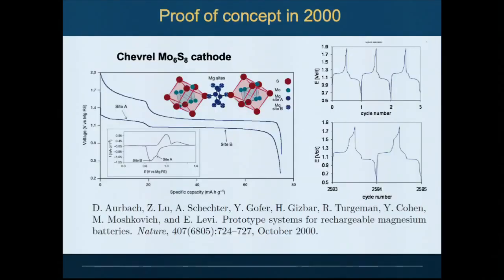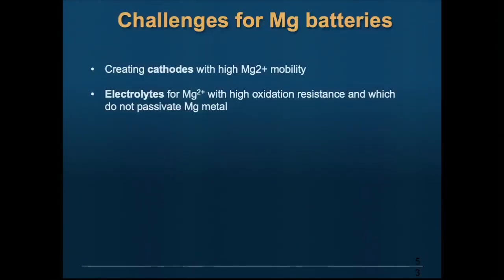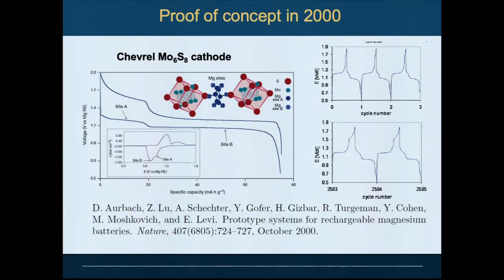So what's the challenge? There are essentially two challenges, right? You need cathodes with very high magnesium 2+ mobility. And that's hard, right? You now have a divalent ion that polarizes its environment a lot, so it's going to be much harder to move. And you need electrolytes that can run magnesium without passivating magnesium metal. Because if we passivate magnesium metal, the game's over. Magnesium oxide is impenetrable. Proof of concept was done back in 2000 by Doron Aurbach in Israel, who showed a working magnesium battery with a Chevrel sulfide cathode. This is remarkable. It runs at room temperature, but the voltage is low, the capacity is low, but it is a proof of concept.